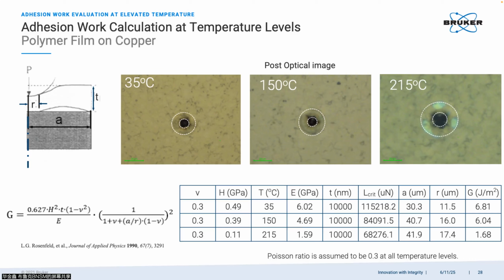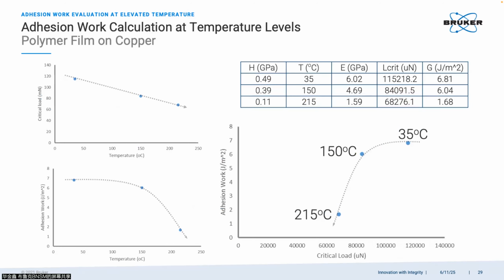Then we have the results here. This is the interfacial bonding changing with temperature. This is room temperature, and this is slightly higher than 200 degrees Celsius. So you can see it is very different. We have two data sets related to the delamination. One is the critical load changing with temperature. So you can see, very interesting, the critical load decreases linearly with temperature.